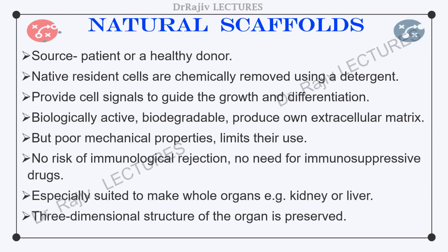Typically, natural scaffolds are obtained by the decellularization of biological tissues, either by dipping tissues in a detergent agent or perfusing them with a detergent via the arterial tree. This removes most or all of the cellular elements from the tissue or organ but leaves the collagen-rich extracellular matrix and intricate anatomical structures almost intact. The decellularized natural matrices serve as a versatile scaffold compatible with stem cell proliferation and specialization.